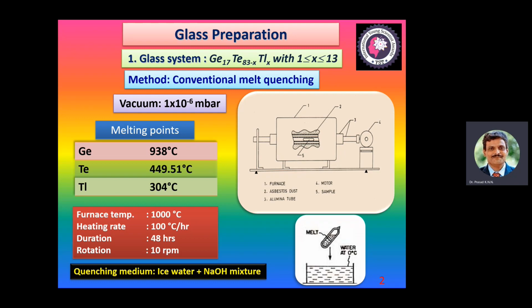Now coming to the method employed for synthesizing this glass, it is none other than the conventional melt quenching technique. For this we used a rotatory furnace which you can rotate horizontally, and for the sake of uniformity we can distribute heat throughout the samples. This rotating furnace is maintained at temperatures of the melting points of the starting elements: germanium, tellurium, and thallium. These are the corresponding temperatures: 938 degrees centigrade, 449.5 degrees centigrade, and 304 degrees centigrade. We have set the temperature beyond 1000 degrees centigrade so that the maximum temperature of all the constituent elements can be covered.